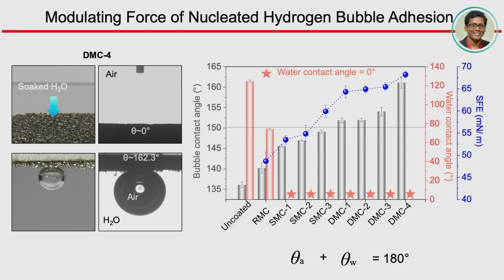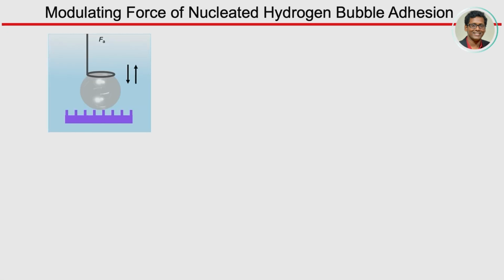So earlier, people used to apply this equation where the aerophobicity plus the water contact angle would be a summation of 180. So if you are making some interface where the water contact angle is 0, people thought it would give you super aerophobicity. But through this particular study, we found that not necessarily is that correct. You can come up with different types of super hydrophilic interfaces, but they are distinct in terms of surface free energy. The surface free energy is a very important term here because that decides how well your interface will be hydrated. The more it is hydrated, the more it will minimize the contact between the bubble and the interface, right? And our assumption was quite correct.